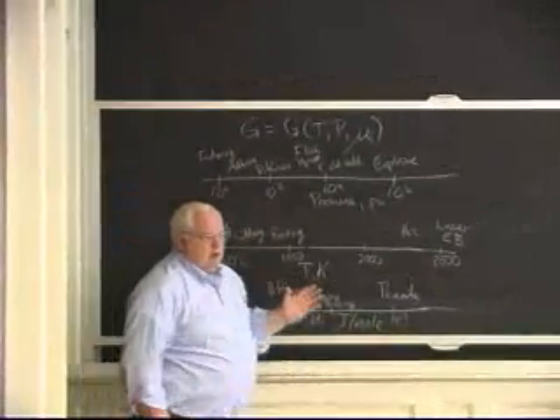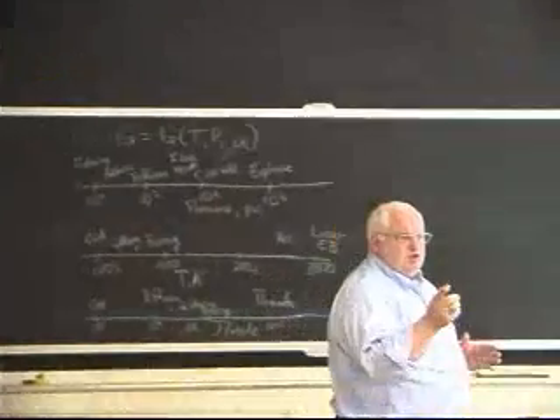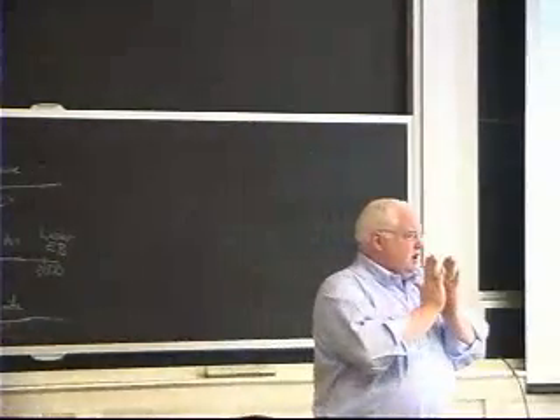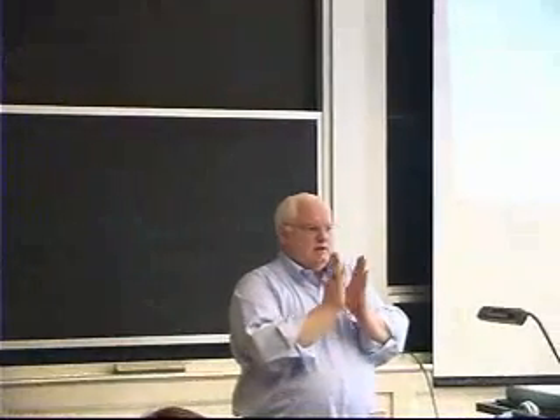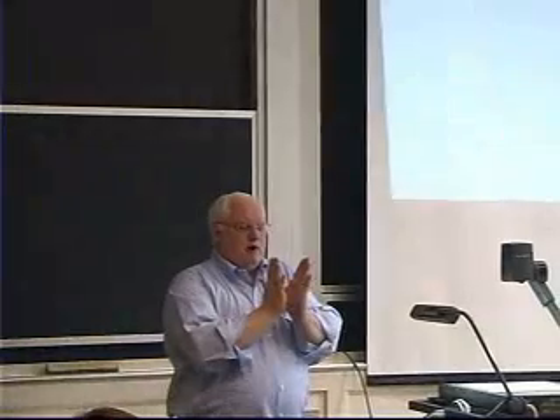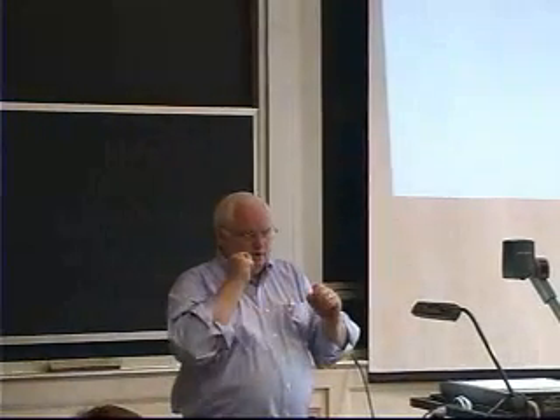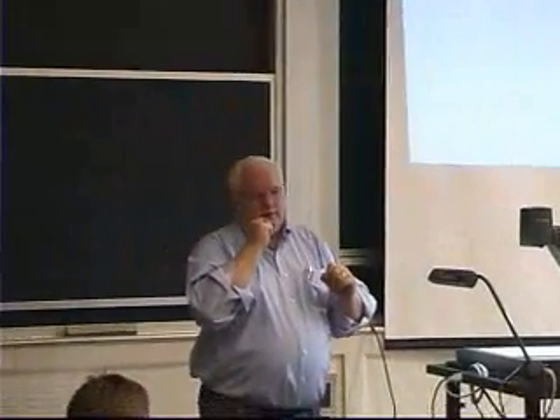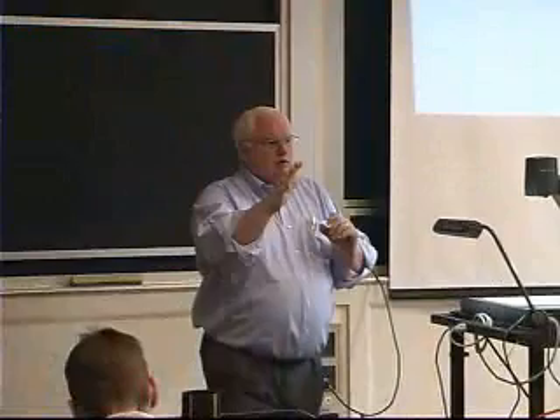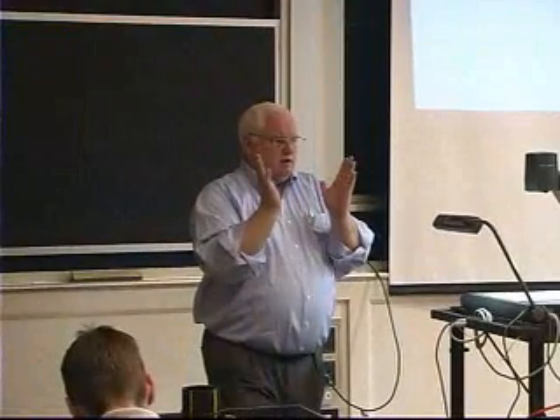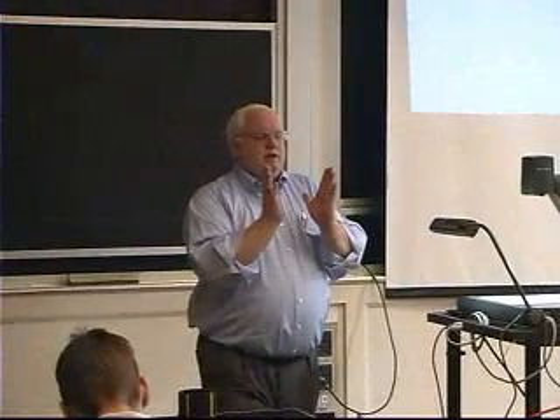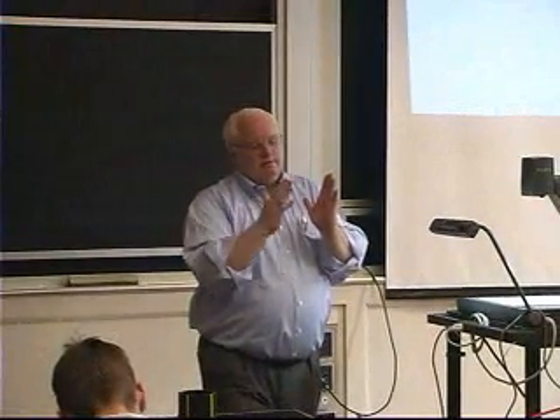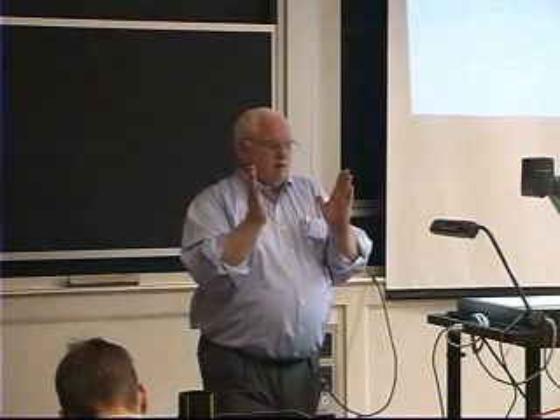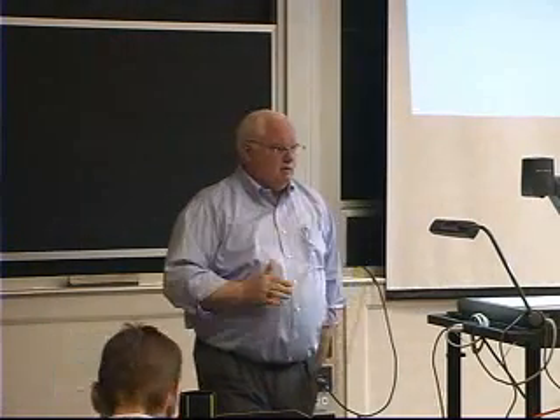Near perfect bond, and that piece I was saying around for Ford, they've already machined the critical angle. In that case, it's not explosive bonding. They're trying to use an electromagnetic pulse. So you give a 10 microsecond pulse of electromagnetic energy, and the eddy currents in the material resist the currents you're putting on, and by Lenz's law, you end up slamming the two things together.